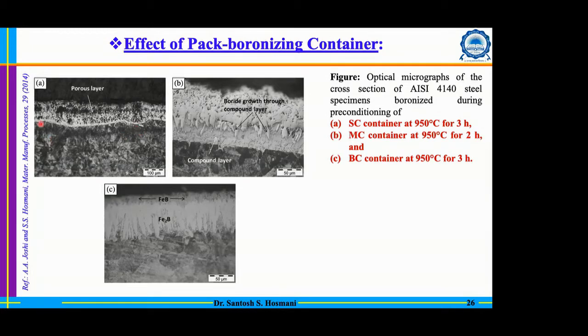And here you can see the effect. In the case of a small container, the boron potential will definitely be limited because the quantity of powder is less. And in this case, we have not found any kind of boride layer as such. This layer is more or less dominated by the sticky layer which is formed there. And there is no boride layer as such in the case of figure A.